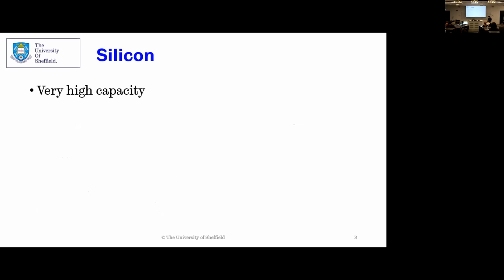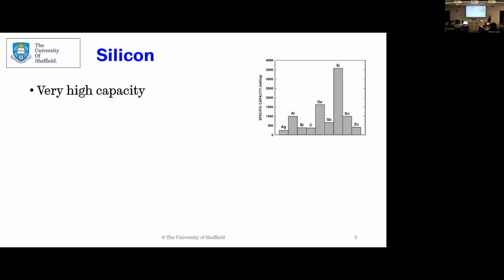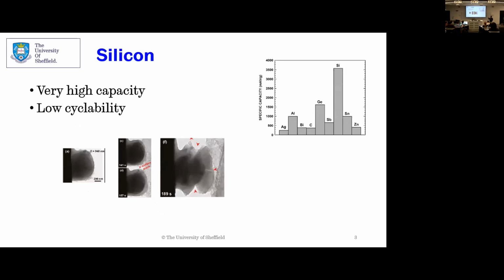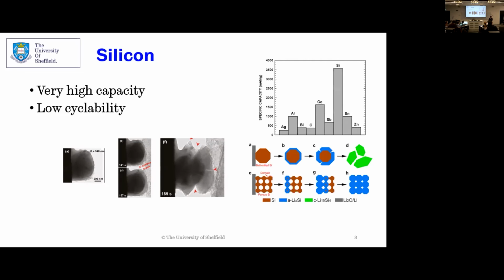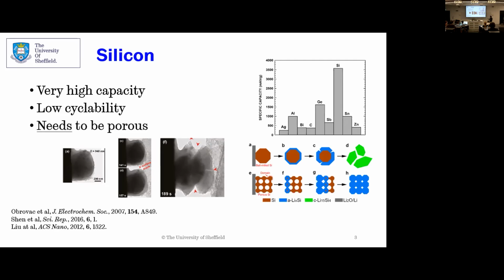So silicon has a very high energy density. You can see here, carbon is down here. It's what we're on at the moment for anodes. When it charges, the particles of silicon expand and they crack. So you get isolation of these particles, not connected to the rest of the battery, so they can't store energy anymore. To combat this, you can make silicon porous, and that means it can expand into its own pore volume and contract without the mechanical stress that causes it to fracture. So it does need to be porous. There are other ways to do it, but this is one of the most promising ways.